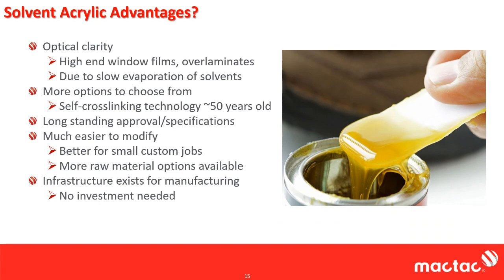One of the nice things about solvent acrylics is that they're much easier to modify, and because of that, they're really better for smaller custom jobs. And what I mean by modify is that tackifiers can be put into a UV acrylic adhesive, or you can put different additives into them, but it's much harder because you got to heat it up and you got to get it molten. And even then, it's still at a much higher viscosity, and you got to have much different types of mixers, specialized mixers that keep it hot.